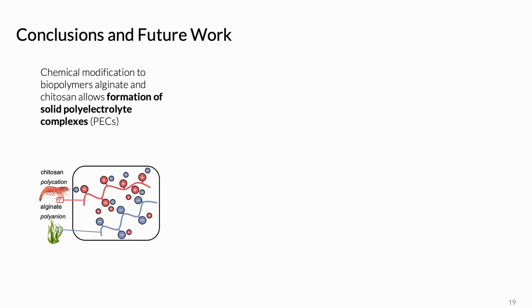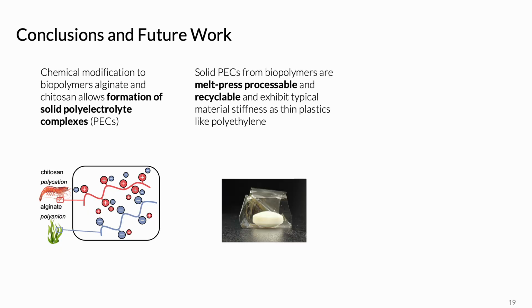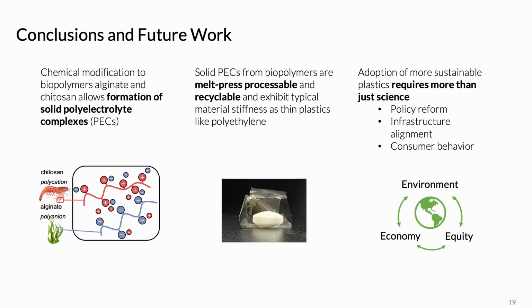In conclusion, I developed a new sustainable plastic alternative out of biopolymers alginate and chitosan by modifying them to form solid polyelectrolyte complexes. And this biopolymer PEC material is processable into thin transparent films, is fully recyclable without chain shortening, and exhibits mechanical behavior similar to polyethylene thin films. All of that being said, the actual transition away from petrochemical-derived plastics and the mitigation of plastic pollution in our environment requires much more than just scientific advancements. In particular, we need concerted efforts in policy reform, infrastructure alignment, and consumer behavior, to name a few, to truly achieve sustainability.